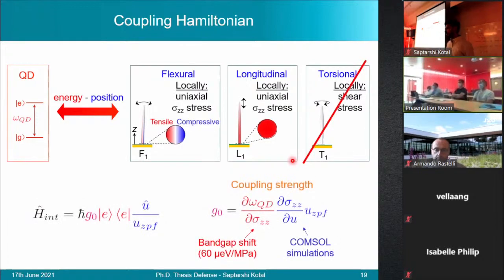The interaction between the modes and the emitter is treated by the following interaction Hamiltonian, where G0 corresponds to the coupling strength. G0 is given by two terms, one in red, which represents the shift in quantum dot band gap per unit of stress applied. And the term in blue represents the amount of stress generated for a given amount of top facet displacement of the nanowire. UZPF is the zero-point fluctuation of the vibration modes.